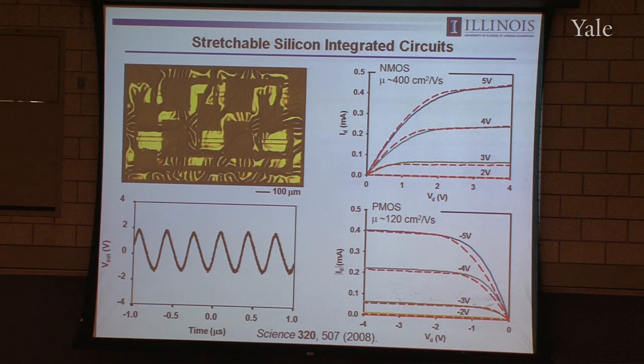So what do the properties of these things look like? This looks like you've taken a perfectly fine integrated circuit and kind of crumpled it up, maybe destroyed it in some way. But it turns out that the waves are fairly modest in their amplitude. Few microns in amplitude, few hundred microns in period. So the actual strains in the materials are modest. And as a result, if you probe the individual devices, as being illustrated here, or the integrated circuit, the performance of this kind of device is pretty much similar to the comparably designed flat geometry. So you've achieved the mechanics you've wanted without sacrificing any of the performance.